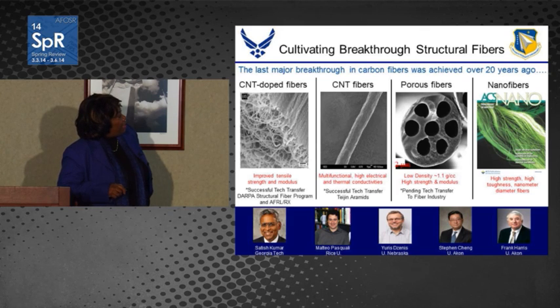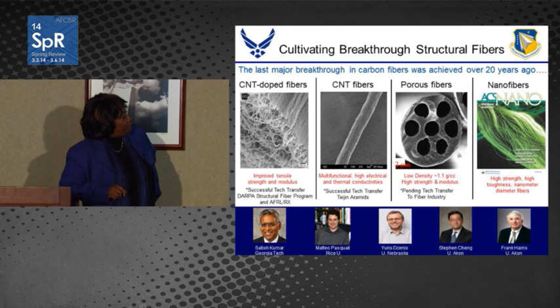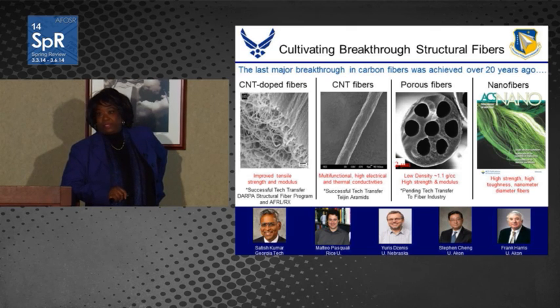Okay, more recently, two other innovations in the area of structural fibers have been, again, the work of Dr. Kumar from Georgia Tech, where he's looking at making porous channel fibers. And so we call this a honeycomb configuration fiber. The objective here is to really decrease the density in these fibers. He's been able to get fibers on the order of 1.1 grams per cubic centimeter, which is getting close to the density of water, so you can make floatable type structures with fibers like this. And so he's been able to process these using, again, his bicomponent spinning process with a sacrificial polymer layer that you can burn out in the carbonization, graphitization steps and end up with these nice channels in the fiber.